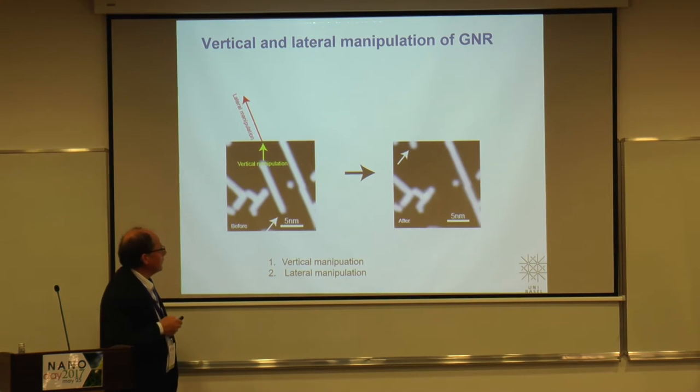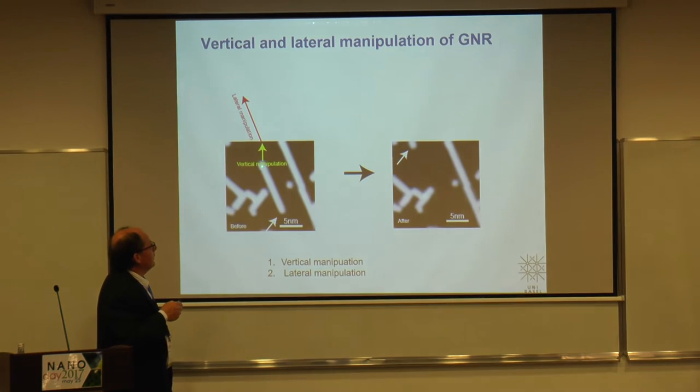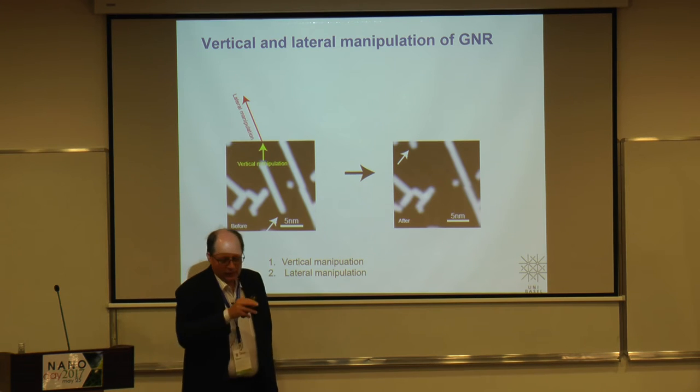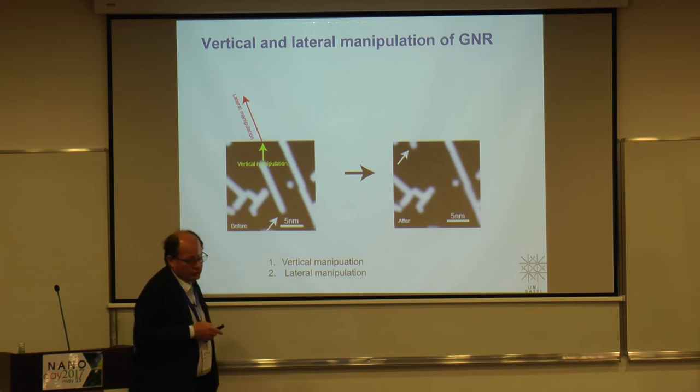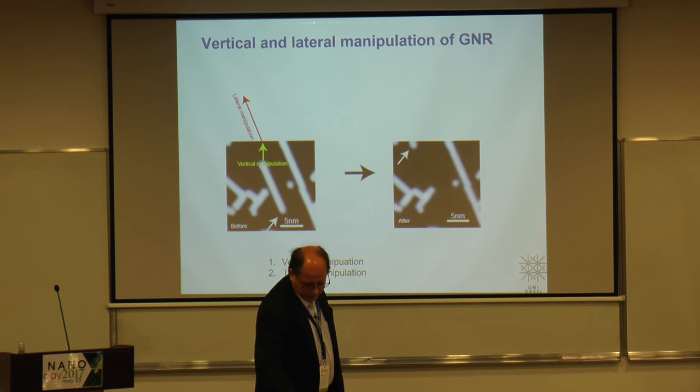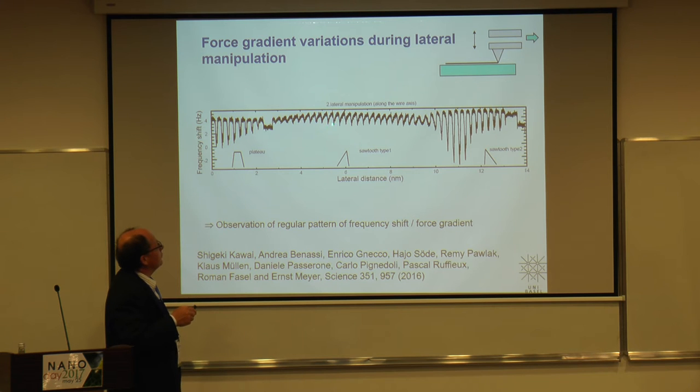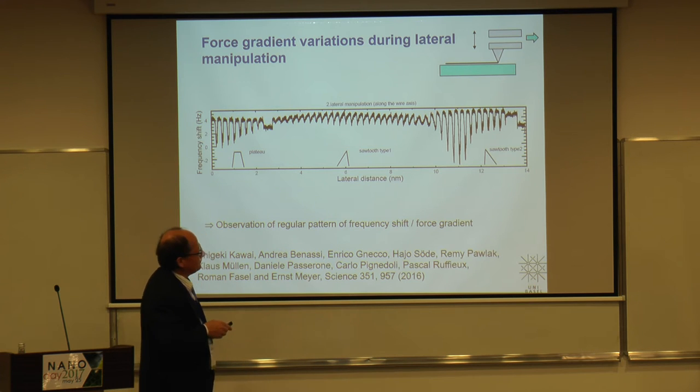Okay, more than that, you can take one of the wires, pick it up with the tip, move a little bit up, and then you can move sideways, so it's really a continuous measurement now of this sort of force doing the manipulation. And you see a nice periodic pattern here, so it's not very large here, these are some hertz frequency shift, but it also shows some like an undulation or like an envelope here of the force, so it varies a little bit with the position.